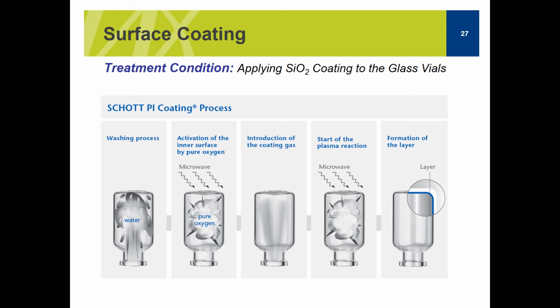Now the second step, what a lot of people are doing, or not a lot of people, but in this case Schott, what they're doing is they're saying, let's forget about the chemical composition of the glass. Let's apply a coating, and let's apply an SiO2 coating. So SiO2, silicon oxide, as you've seen from the video, is basically the purest form of glass. And if we use that as a coating, then we have a lower risk of delamination, or a lower risk of having a lot of extractables and leachables, and it works to a certain degree.